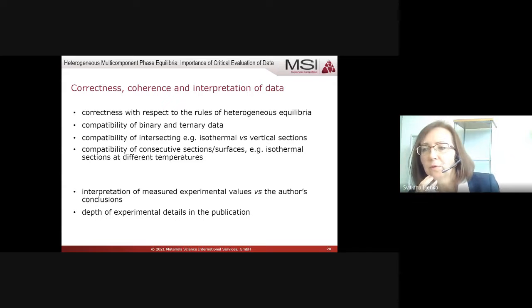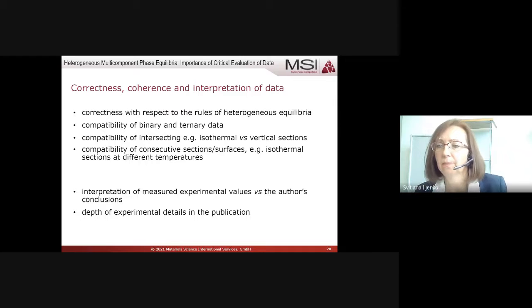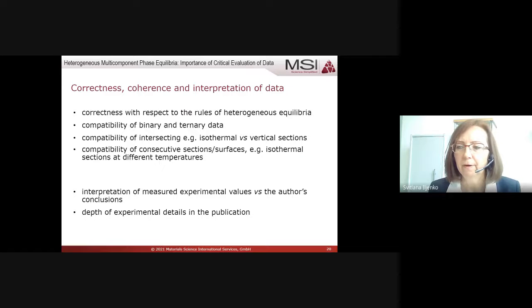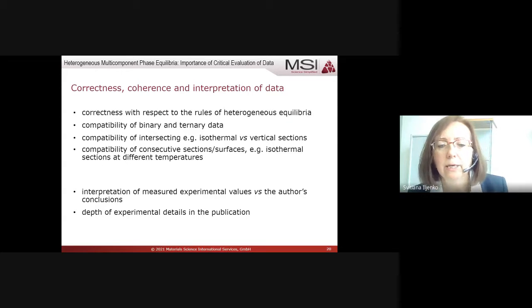And indeed, if the raw data are given in the original article, our experts may reinterpret this data and come up with a different phase diagram. And this indeed happens often, or at least partially. Therefore, the depth of experimental details in the publication is also an important parameter that helps to verify the reliability of the published data. And therefore, I'm always encouraging scientists: when you publish your data, please give as much data as possible, raw data, measured data, just measurements in table form, DTA curves and so on. This is really helpful for other scientists when looking at your publications.